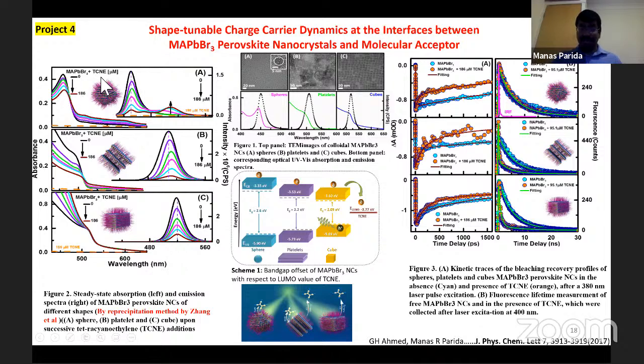So in that way, if we compare the absorption and emission graphs similarly, there is a change in absorbance, there is a quenching in absorbance, and there is another thing I want to mention here. When you are adding some acceptor here and after that exciting the system, you are exciting only the donor. Earlier we were exciting the porphyrin, and here we are exciting only the perovskite. We are not exciting the acceptor, because you see if I excite here, the acceptor has no absorbance. Okay, so as there is no absorbance, there is no emission. So once you are exciting with any pump light, you are only exciting the perovskite. Okay, so once you excite the perovskite, definitely the electron transfer is only possible from the perovskite to the acceptor. The opposite cannot be possible. Okay, and similarly you can see the images of the spheres, the cubes, and here the plates. Also, this is not very clear.